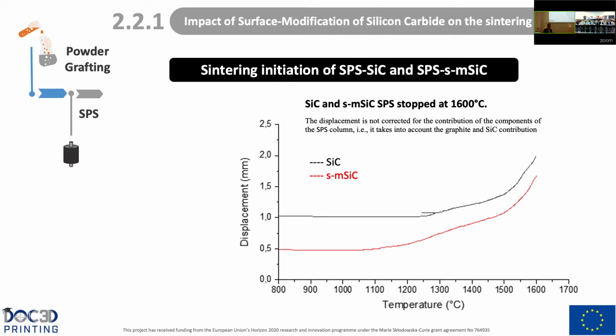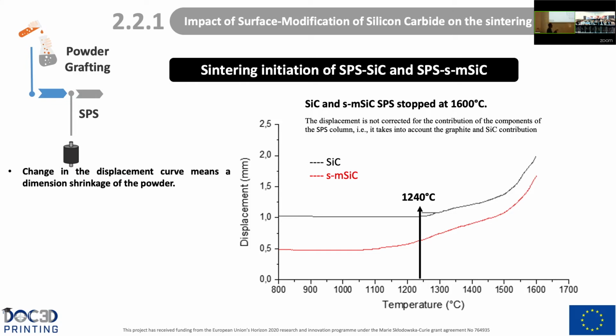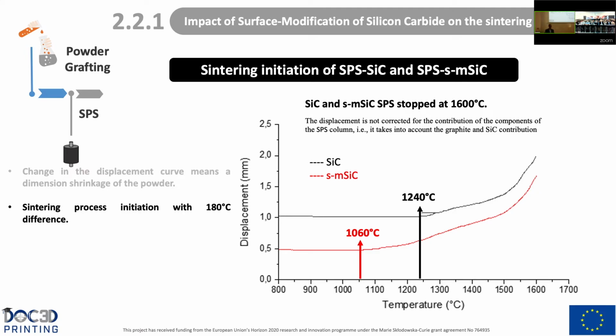So now we are going to use the silicon carbide and surface modified silicon carbide experiments that we stopped at 1,600 degrees to study the sintering of both powders. So for this, here we can see the profile of temperature and displacement, and actually a change in the displacement curves, as we can see here, means dimension shrinkage of the powder. Specifically for the silicon carbide powder, this is happening at 1,240 degrees, and for the surface modified silicon carbide at 1,060 degrees. So actually, we observe that the sintering process initiation has a difference of 180 degrees.